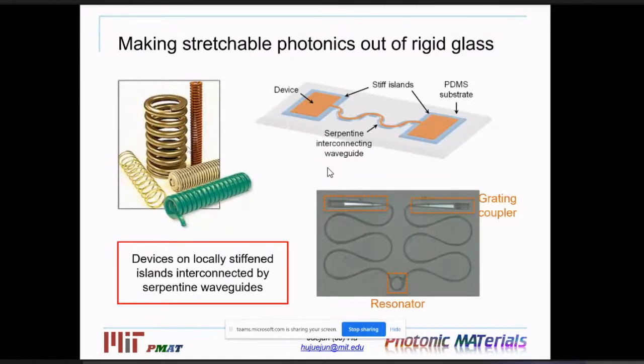So what we did is essentially create an on-chip photonic spring. We were able to create waveguides with a serpentine geometry. Our mechanical analysis found that when you stretch such a structure, it deforms both in plane and out of plane, and in the process relaxes most of the stretching deformation.